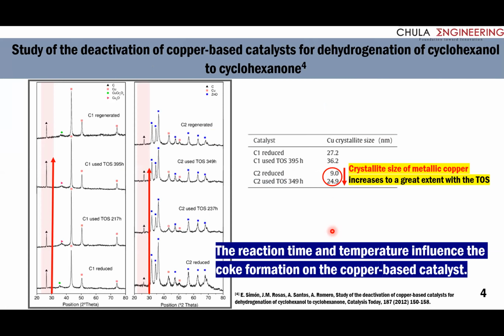Simon et al. 2012 focused on the deactivation of copper-based catalyst for the dehydrogenation of cyclohexanol to cyclohexanone. XRD analysis evidenced the presence of coke deposited at a high time on stream, while the simultaneous decrease of the relative copper concentration and the increase of carbon concentration suggest that coke deposition takes place preferentially over the copper active sites. The XRD is shown in this figure. The carbon content increased with time on stream, about 7.67% weight.